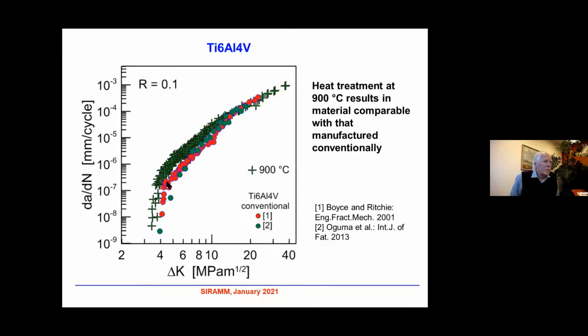And now let me compare our data, our measurements on our specimens, with material which is manufactured conventionally. There are data by Boyce and Ritchie and Oguma, these red and green points. What we can see is that our material is practically the same, somewhat worse in this area than the conventional material. So if we set the parameters of 3D printing very well and do the heat treating very well, we can reach material which is comparable to the conventionally produced material.